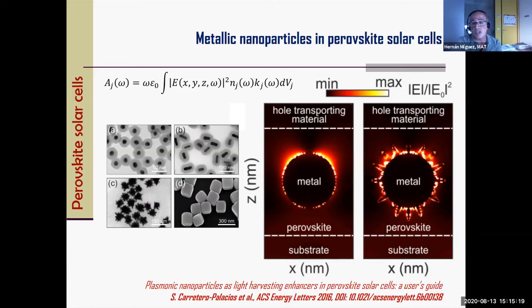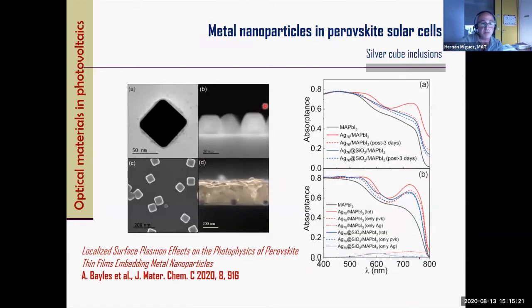So this is what we did experimentally. This is the experimental realization, not of the cell, but of the integration in the perovskite film. So this is a 200 nanometer perovskite film with metallic particles integrated in it. These are the metallic cubes that we synthesized for that. And this is the demonstration that you can actually improve the absorption in a wide spectral range, just like the theory says. So this is theoretical, this is experimental.